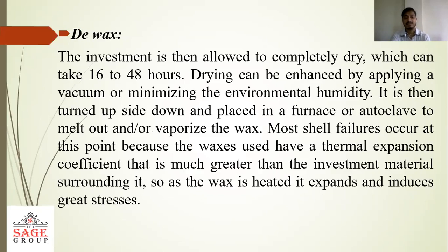Dewax. The investment is then allowed to completely dry, which can take 16 to 48 hours. Drying can be enhanced by applying a vacuum or minimizing the environmental humidity. It is then turned upside down and placed in a furnace to melt out or vaporize the wax. Most shell failures occur at this point because the wax has a thermal expansion coefficient that is much greater than the investment material surrounding it. So when the wax is heated, it expands and induces great stress.